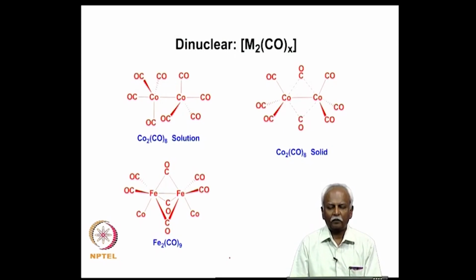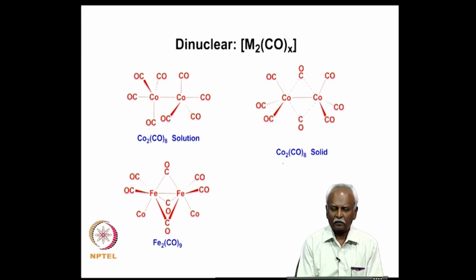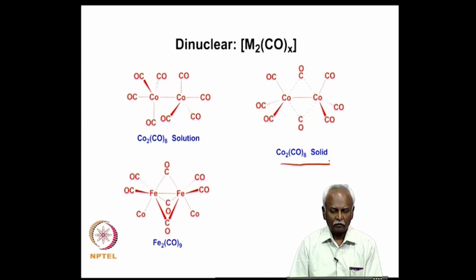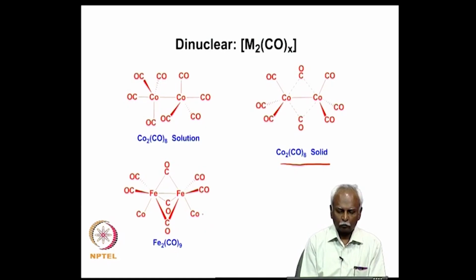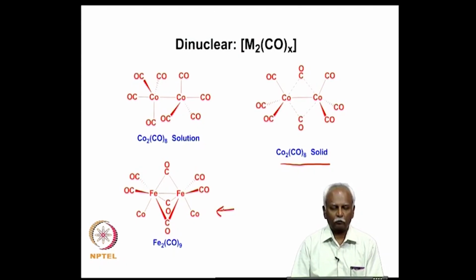So, here I have pictured the two structures of the dicobalt octacarbonyl complex. In the dicobalt octacarbonyl complex, in solution you find there are no bridges, and in the case of the solid state structure you have a very clear indication of a bridge structure. In the case of diiron nonacarbonyl, that is Fe2(CO)9, you find that there are three bridging carbonyls, and that invokes the necessity of a metal-metal bond in order to satisfy the electron count.